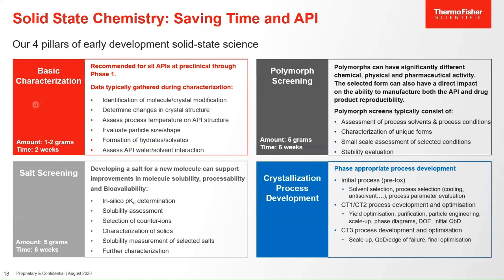So this is collecting physical data on your API, melting temperature, DSC looking for phase transitions, TGA looking at stability, an X-ray diffraction pattern as a benchmark for characterization later on, checking whether you have a solvate or a hydrate, and so on. And then we have 3 further packages that are screening packages. One is a polymorph screening package, one is a salt screening package, and the third is a crystallization process development package.